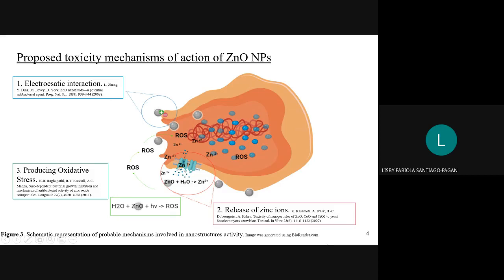Zhang and coworkers suggested that there are strong electrostatic interactions between the nanoparticles and the bacterial cell that damage the cell membrane. Here they suggest that the zinc oxide nanoparticles are positively charged when they are suspended in water, and thus they can interact with the negatively charged bacterial surface, which then leads to the membrane disruption.